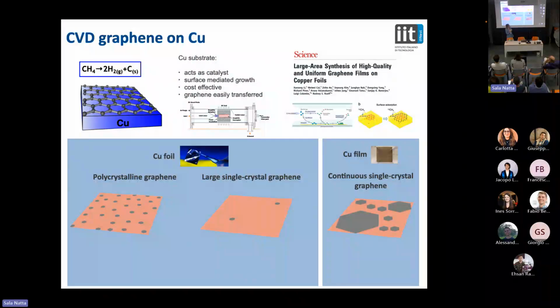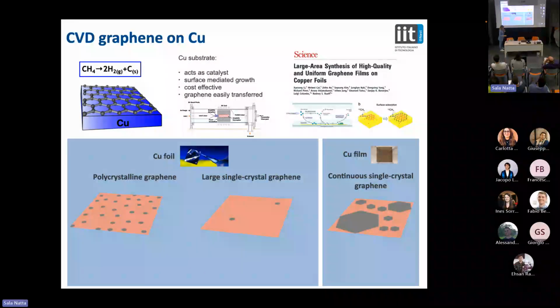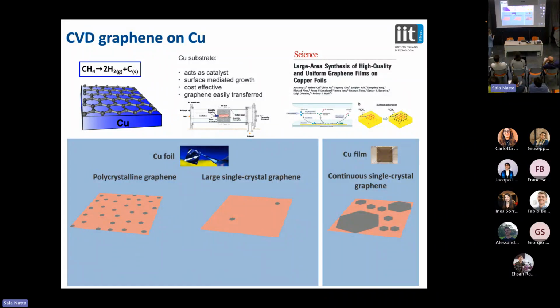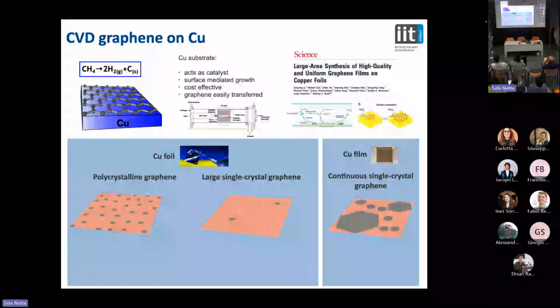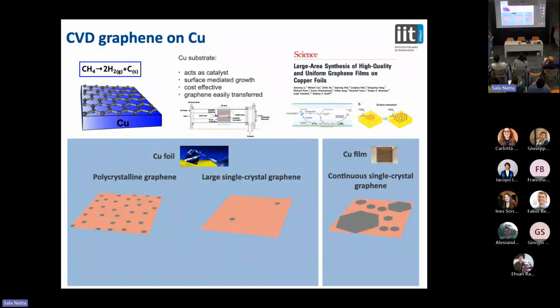And what we do, well, actually I should have put an image of our reactor, but on top of there you can see a horizontal reactor over there. I also have a pointer. Why don't I use it? So you can see this, and you can see that usually you will have inlet with where the methane enters. You don't flow only methane, you also need to flow carrier gas like argon, hydrogen, and so on. Argon is a pure carrier, just a heavy fat atom which helps to push other atoms in. Hydrogen is more catalytically active, actually also can help reaction to happen.